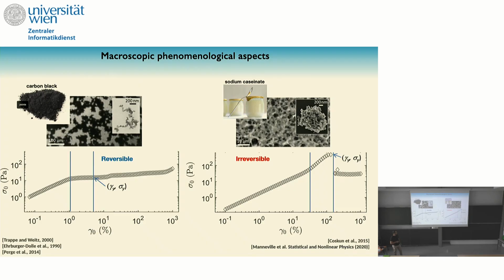And here you have also the stress as a function of the strain, and you recover a linear regime. You get some nonlinear regime here where the system is getting stiffer and stiffer, and then eventually it will break, or you have a failure here, a fracture, and then the system never recovers.